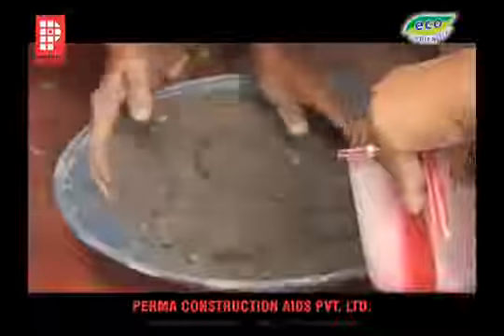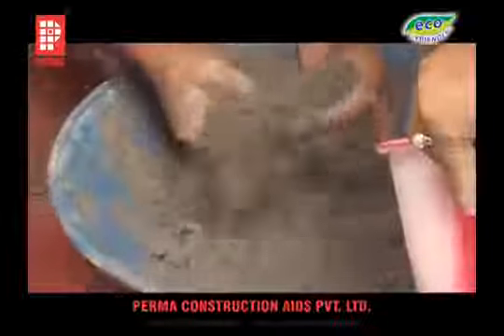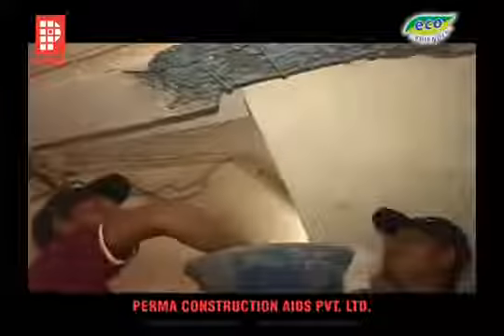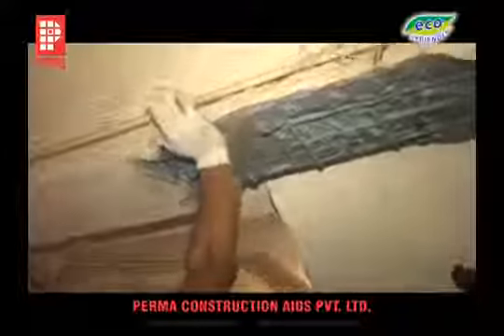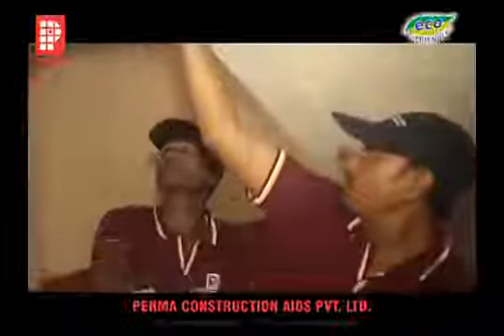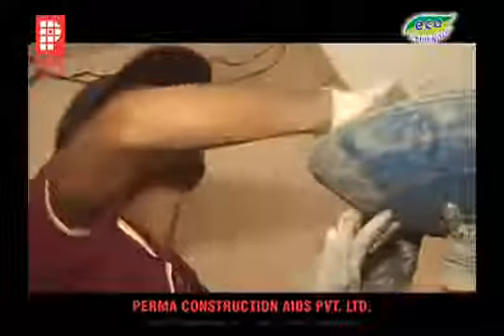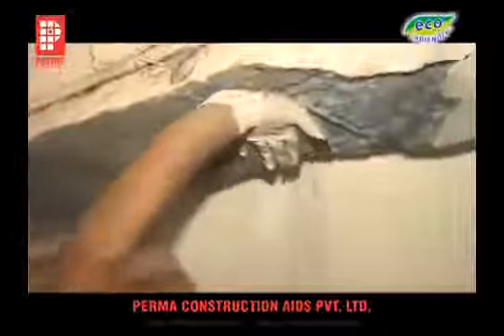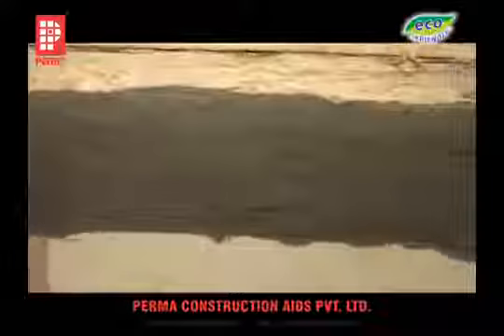This mortar is applied on the SBR and cement slurry applied all over the broken concrete and the reinforcement as a bond coat. The mortar is hand-packed in layers of 20 mm. Further build-up is achieved in layers of 20 mm on a mechanical key, created on the first mortar layer when it is still soft and on the fresh bonding slurry applied. This mortar is usually stronger than the parent concrete.